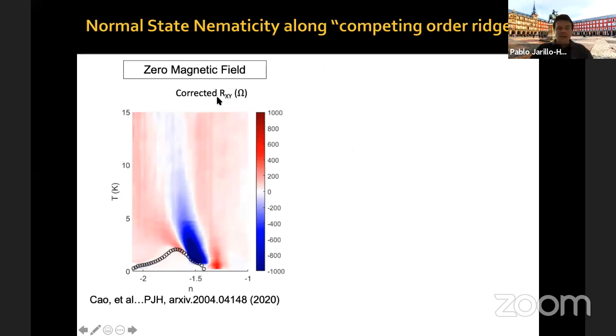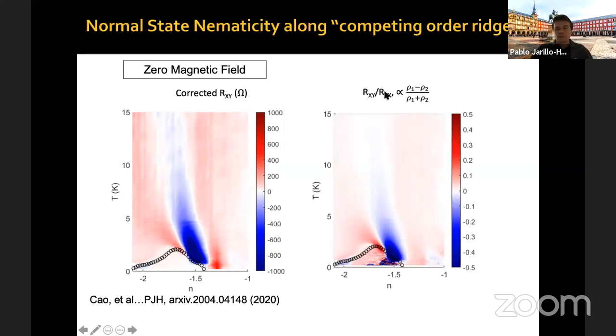I'm showing you in this data actually a corrected RXY, just trying to correct for any possible artifact, such as rho XX, rho XY misalignment in the electrodes, et cetera. And the more we correct it, actually the stronger the anisotropy becomes. It becomes particularly strong in this region, what I showed you before. We also have this resistivity wedge. In fact, you can divide RXY by RXX, and you can see that this is an extremely strong anisotropy of order 50%. So this is a very strong anisotropic system, much more than one would have naively expected.